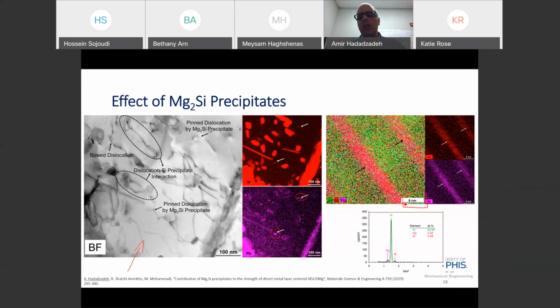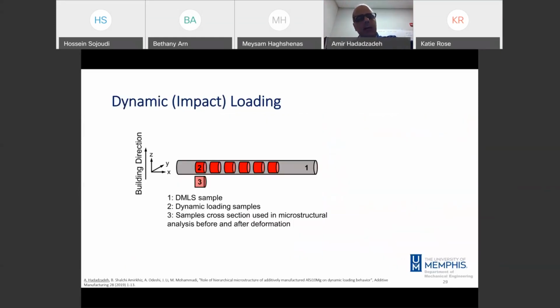This scale is 8 nanometer, and this kind of map is very unique because it's very difficult to obtain such a map at this scale using TEM. So Mg2Si in some cases can play a role in the strength of the material. I jump to the next part, which is dynamic or impact loading.